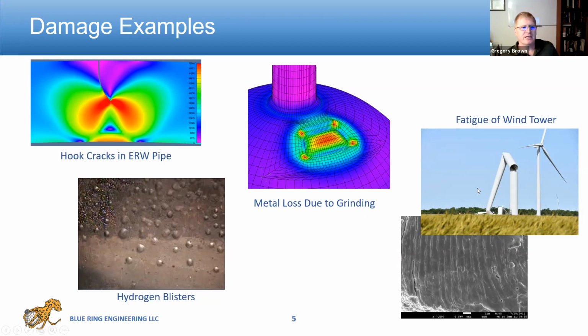Here's another example of fatigue damage. This is a wind tower. There's a lot of interest in renewable energy now. A wind tower is basically a beam that bends in the wind. If you have a crack, that crack can grow and eventually cause catastrophic failure that you see here where you collapse the tower. If you looked at failure surfaces on that wind tower, you might see fatigue striations, which you see in a scanning electron microscope. Very obvious that this is growing by fatigue.